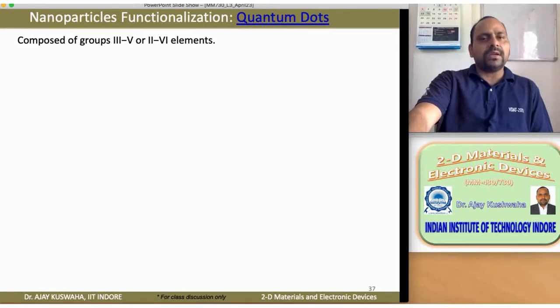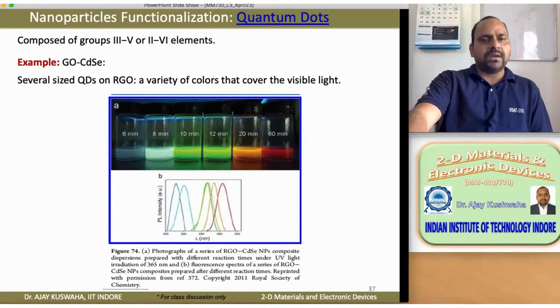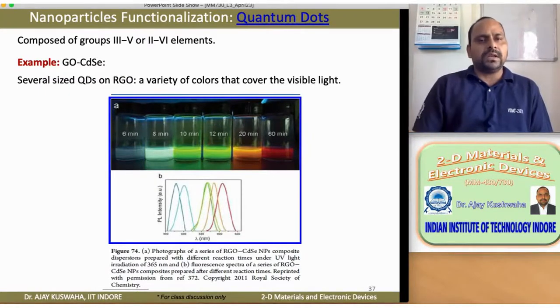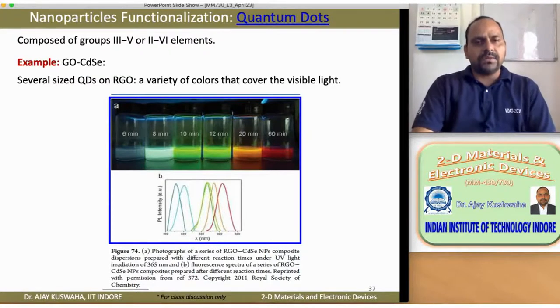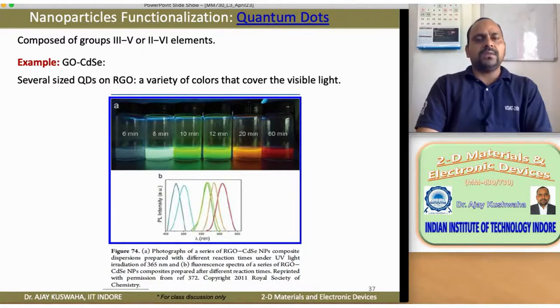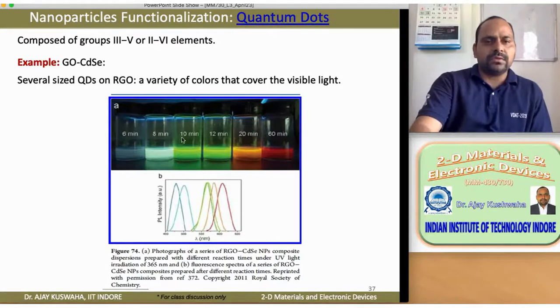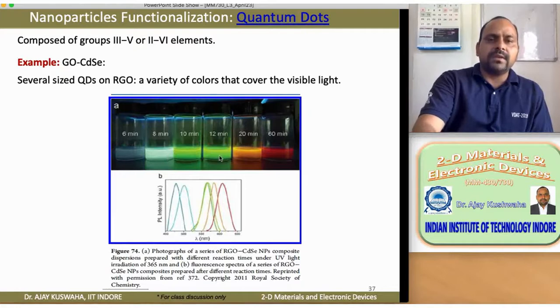Another possibility is we may have quantum dots of group III-V or group II-VI elements. One example is the CdSe quantum dot, which is functionalized with graphene oxide. You already know that if we have a variation in the size of the CdSe, there will be a difference in the color of the particles. If you illuminate with UV light, then we are going to see different colors. That basically gives us the idea about quantum confinement. So that property will be retained if we modify the graphene oxide with CdSe particles, and they have shown very good data here, from 6 minute to 60-minute functionalization, which gives the difference in size, and once the difference in size is there, we can see the difference in color. So this is the suspension of GO and CdSe functionalized particles.